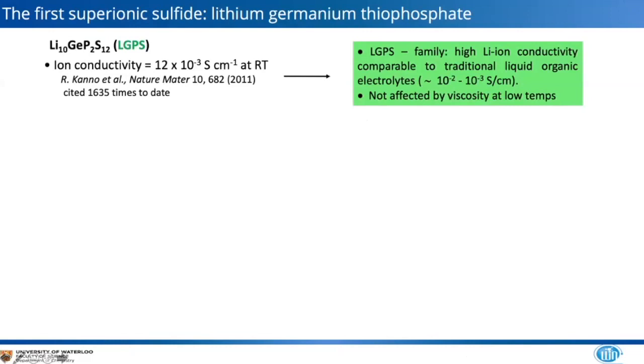So the first superionic sulfide arguably is lithium germanium thiophosphate. This was reported by Ryoji Kanno in 2011, and it really opened up the field. So this is often quaintly known as LGPS because of its formulation, and it's reported to have ionic conductivity in the order of 12 millisiemens at room temperature. And so this makes that conductivity comparable to traditional liquid organic electrolytes. And the solid electrolytes are not affected by viscosity at low temperature, which gives them good low temperature performance, at least comparable to liquid electrolytes, if not better.